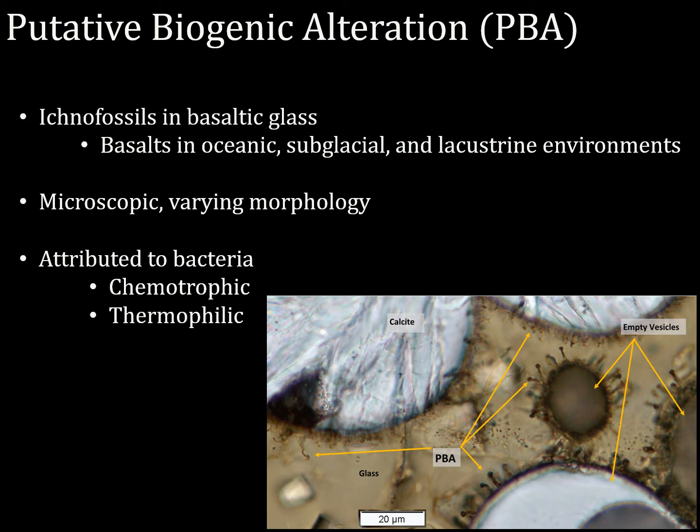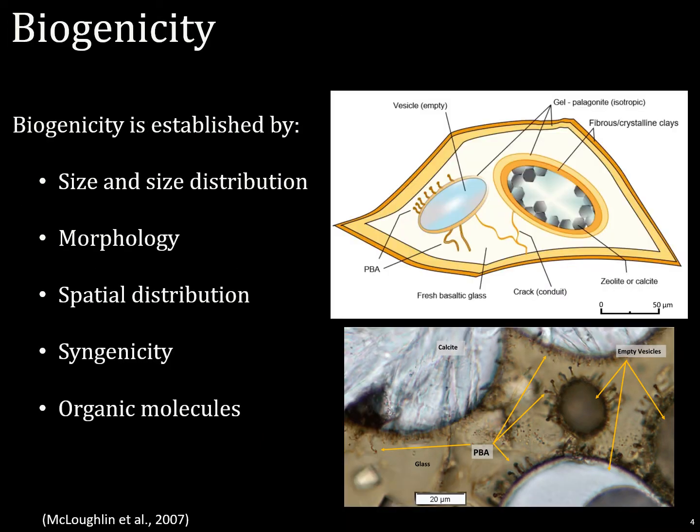And the organisms that cause them are chemotrophic, meaning that they don't need oxygen to perform their respiratory and metabolic functions. They can use other oxygen donors, such as metals. And they're thermophilic, which means that they like to be warm, 60 to 80 degrees Celsius typically for thermophiles, over 80 degrees Celsius for hyperthermophiles. So this is the type of thing that you would find in hot springs at Yellowstone. So how do they do what they're doing? The microorganisms, the bacteria, can create a microenvironment around themselves that could be highly acidic or alkaline depending on the organism, and that causes a dissolution of the volcanic glass.